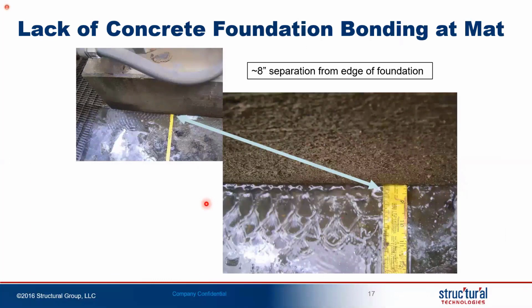Sometimes the concrete foundation is not bonded well with the concrete mat down below. Here's an example where a measuring tape was stuck underneath the foundation below the pump base, and they were able to stick it in there almost 8 inches. So there's not a good bond there between the concrete foundation and the concrete mat, and that can result in increased vibration of the pump and motor.